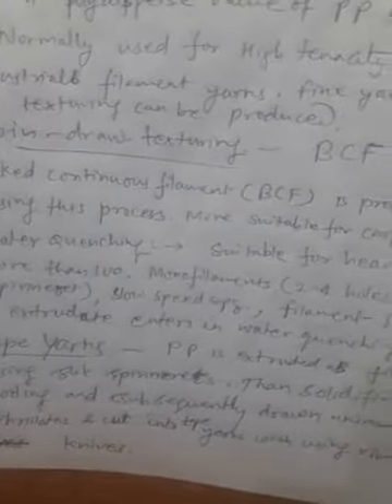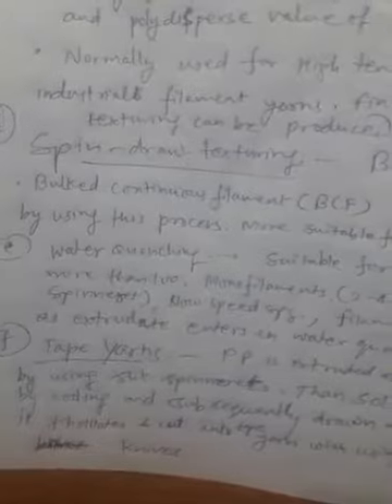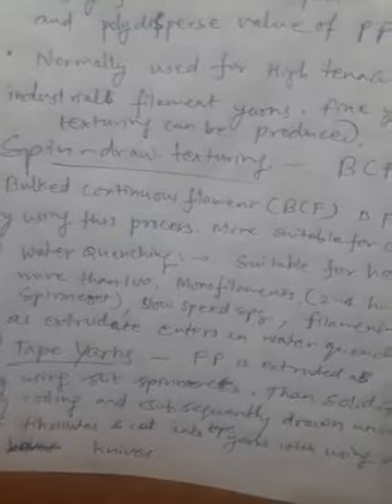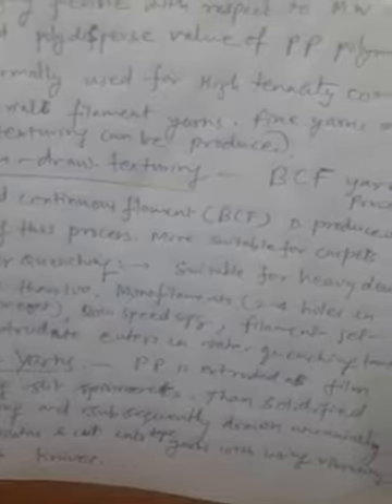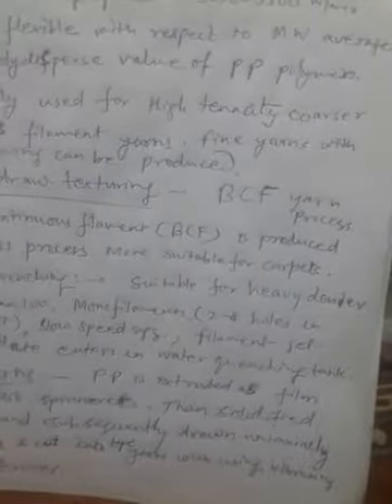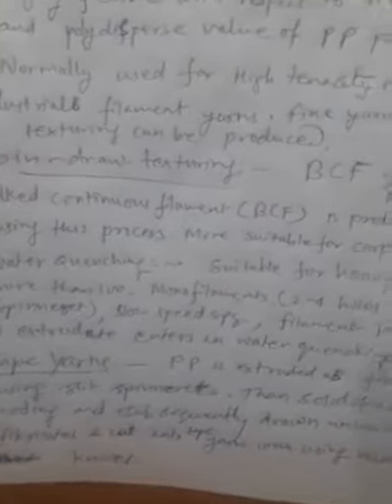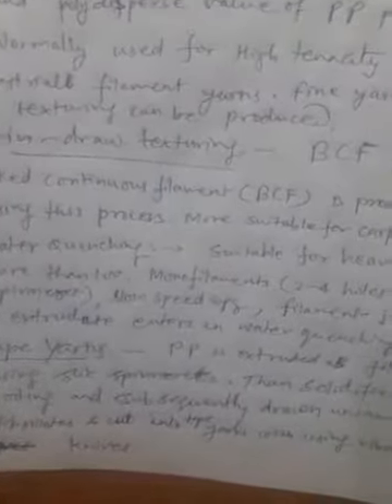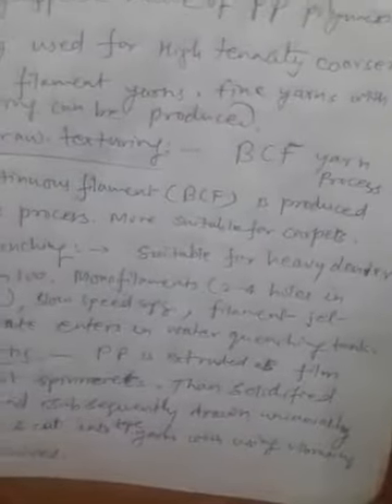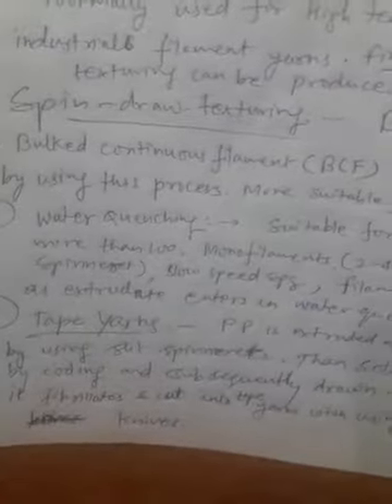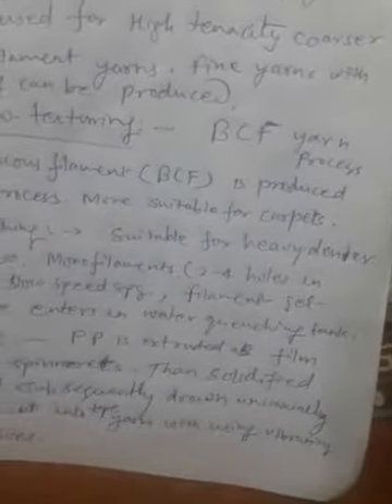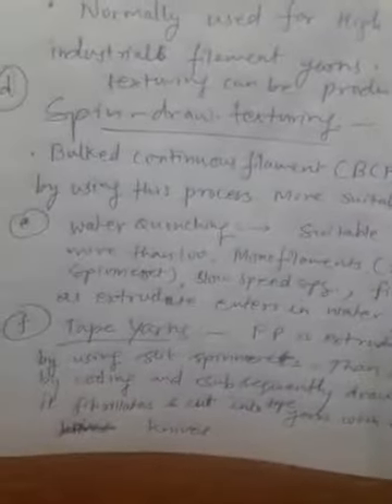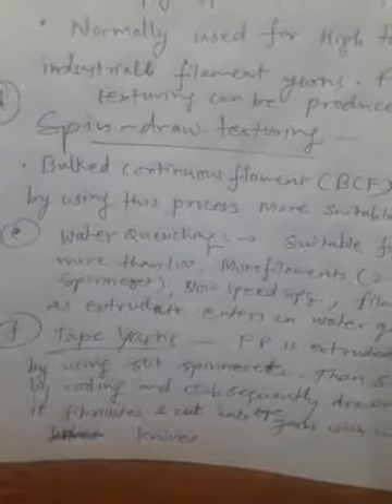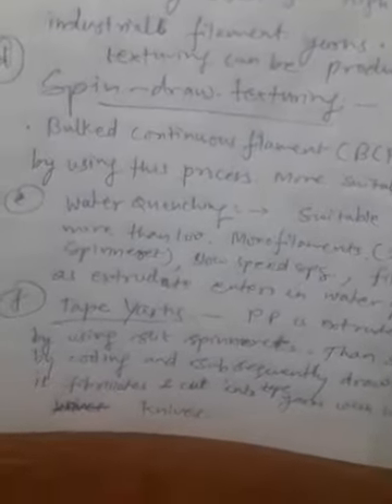Now another important method is water quenching, and that is suitable for heavy denier yarns, 100 or more than 100 denier filament can be produced, and you can say these are monofilaments, and 2 to 4 holes in the spinneret you can see. And just immediately after that, slow spinning speed is kept, the extruded filament in a liquid stream comes out and enters a water quenching tank.